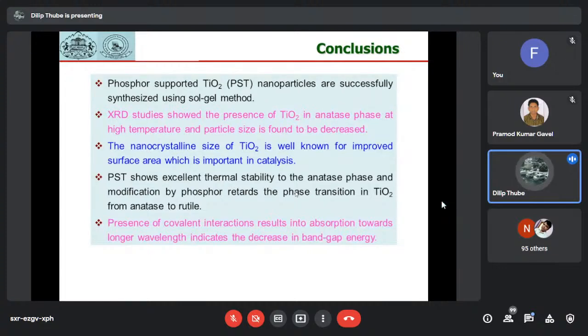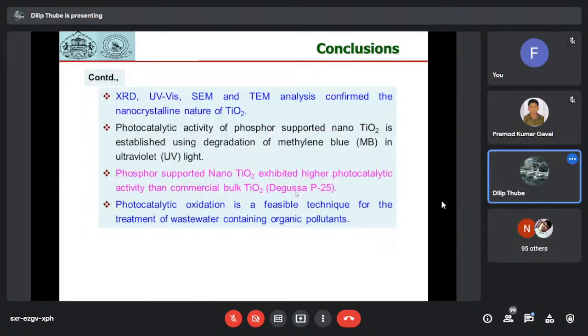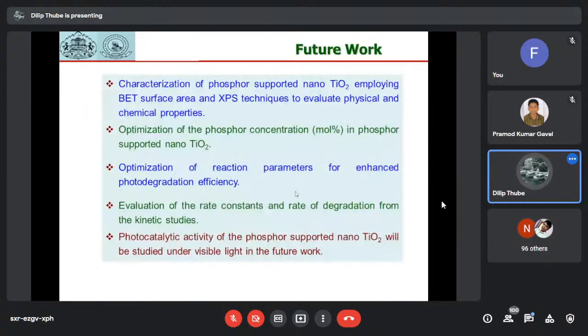Presence of covalent interaction results in absorption towards longer wavelength, which indicates a decrease in band gap energy. XRD and UV-visible analysis confirm the nanocrystalline nature of TiO2. Photocatalytic activity of phosphor-supported nano TiO2 materials has been established using degradation of methylene blue in UV light. Phosphor-supported nano TiO2 exhibited higher photocatalytic activity than a commercial bulk TiO2 material, that is the Degussa P25 sample. Photocatalytic oxidation is therefore a feasible technique for the treatment of wastewater which contains organic pollutants.